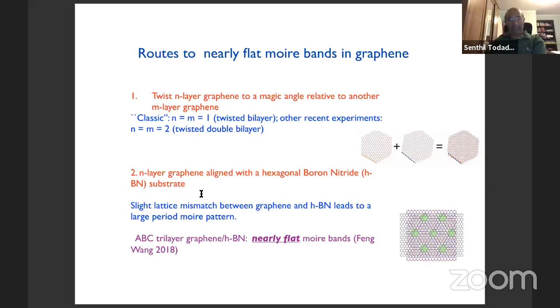Now, yet another route is to not do any twisting at all, but rather to take N-layer graphene and align it with a hexagonal boron nitride substrate. Many of you probably know this, hBN is a very popular substrate for graphene experiments, but there's a slight lattice mismatch between graphene and boron nitride, and the slight lattice mismatch leads to a large period Moiré pattern. And this Moiré pattern, again, reconstructs electronic bands and does all kinds of interesting things. So this was demonstrated first very nicely in some beautiful experiments by Feng Wang on ABC stacked trilayer graphene, nearly aligned with hexagonal boron nitride. And he showed that you get correlated electron physics in that system as well.